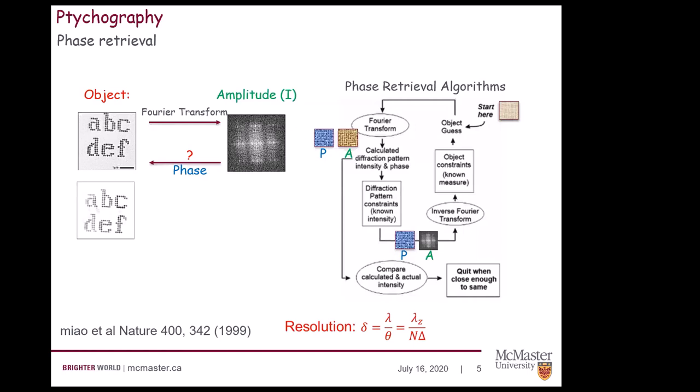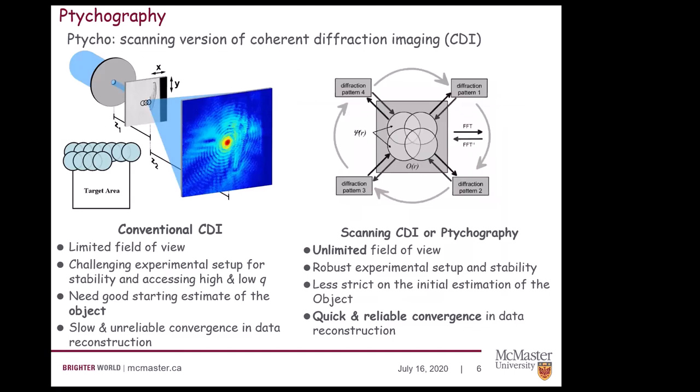The resolution depends on the wavelength of the beam source and the distance from the diffraction spot to the center of the detector, which is the Q value. The center part of the detector captures low-frequency components, while the fine detail is in the outer part of the CCD camera. Based on CDI, the field of view depends on the spot size illuminated on the object. Ptychography is a technique to overcome the challenge of achieving both large field of view and high spatial resolution simultaneously.